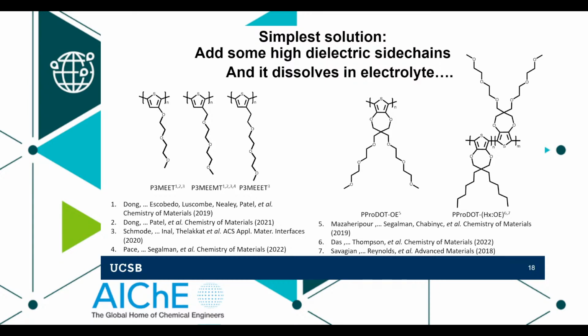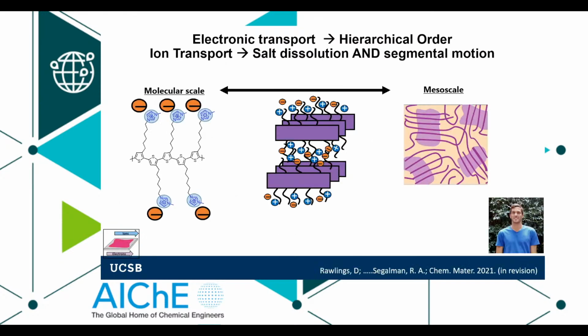The problem is that, at least in our hands, every single one of these over time starts to dissolve in the electrolyte. Because what we did was we increased the dielectric constant, we made it more similar to the electrolyte, and slowly the electrode starts to dissolve, which is not what you want overall. Okay? So that puts us in a corner where we have to start thinking about how do I get hierarchical order for the electron transport while also maintaining an ability to do ion transport. And that makes us think at multi-scales.